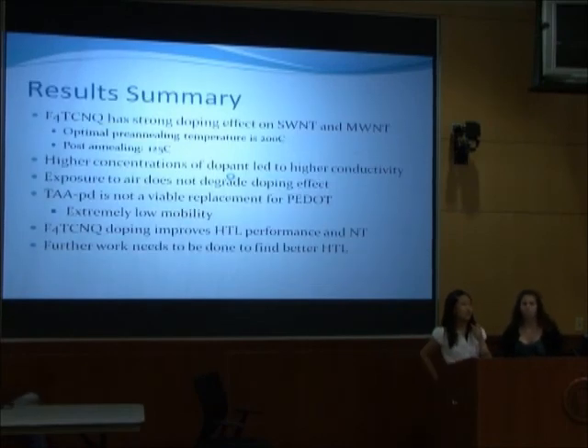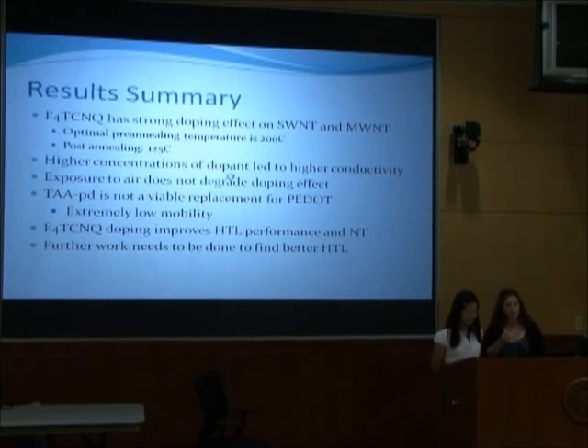So, in conclusion, we found that F4TCNQ has a strong doping effect on both single-walled and multi-walled nanotubes. The optimal pre-annealing temperature for the nanotubes is 200 degrees centigrade, and the post-doping annealing temperature is 125 degrees centigrade. We discovered that higher concentrations of dopant led to higher conductivity. However, at a certain concentration, the doping effect becomes saturated. Prolonged exposure to air does not degrade the doping effect we observed on our devices. TAPD is not currently a viable replacement for PEDOT:PSS, chiefly because of its extremely low mobility.